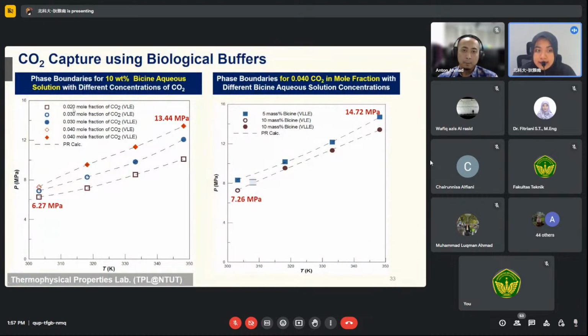Ya, nah di sini ada perbedaan konsentrasi, with fixed mass fraction of the bicine aqueous solution with different concentration of CO2. So we varied concentration. That's why if you compare with the ionic liquids, right, this is just 0.02. It's very, very small. But the ionic liquids, you can measure up to 0.5 or 0.1. Why? Because we have aqueous.